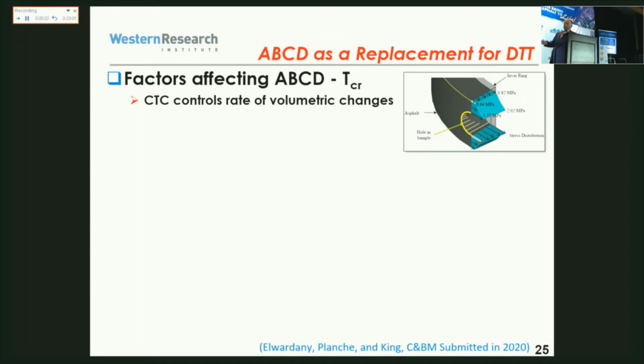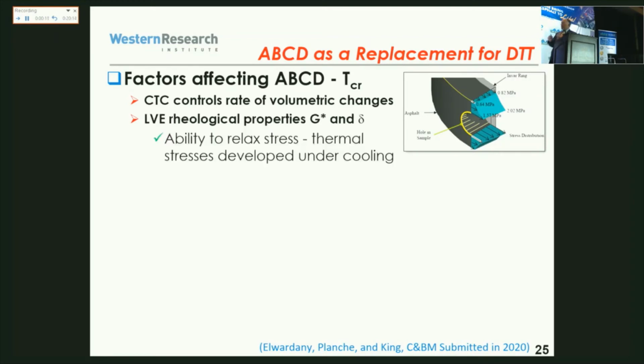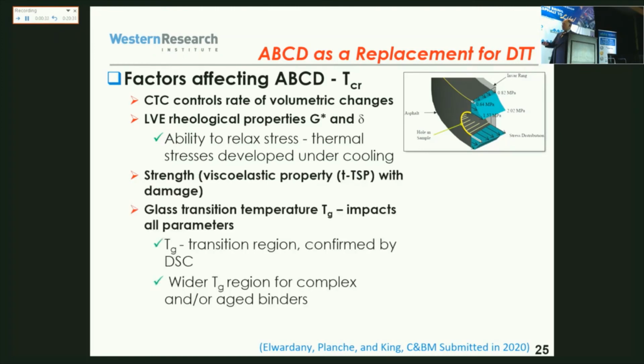There are many things included in this test. First of all, the coefficient of thermal contraction is included in the test, and that controls the volumetric changes, which is what happens when the binder is submitted to low temperature: it shrinks. It's also impacted by the rheological properties, so it's hidden, but it's part of it. The strength is part of it. And the glass transition temperature, which is a fundamental property, is also related to this test.